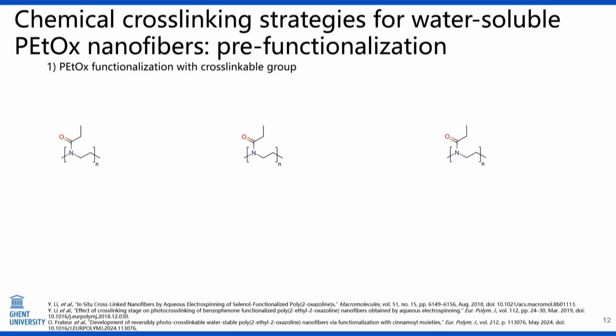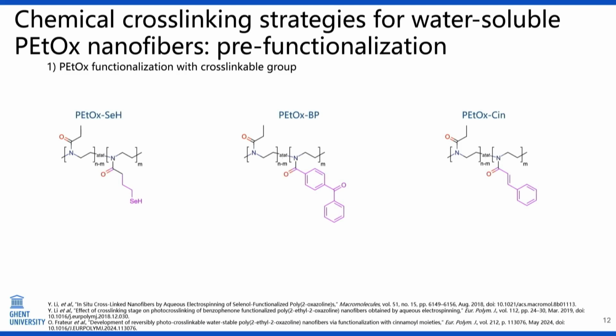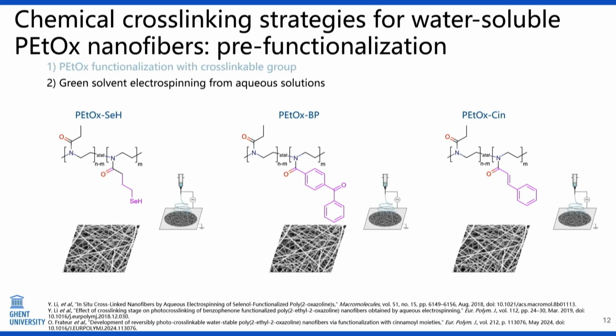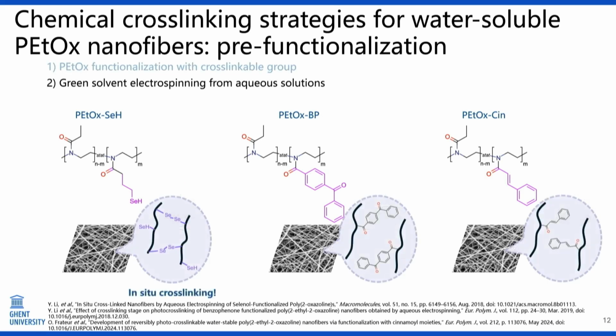First strategy is chemical cross-linking, and we've done quite some work on chemically cross-linking the PEtOx, as this is a very important member of the family, which is the most widely accessible and commercially available. For that, we've introduced a comonomer functionalized with a cross-linkable group, and we've used selenol groups, benzophenone, and cinnamoyl groups here.